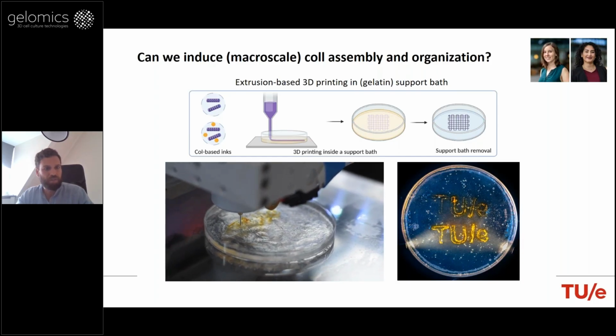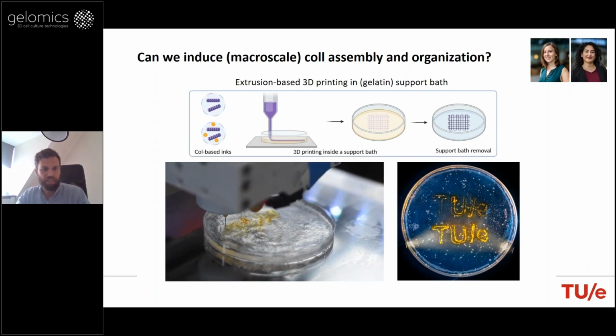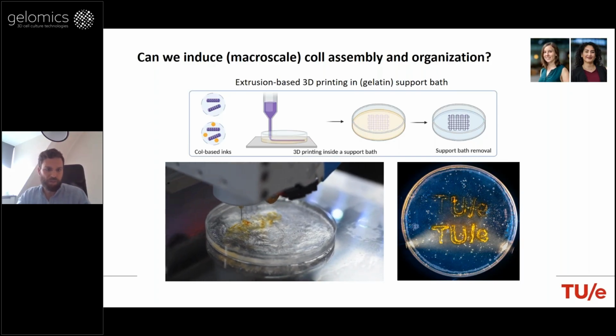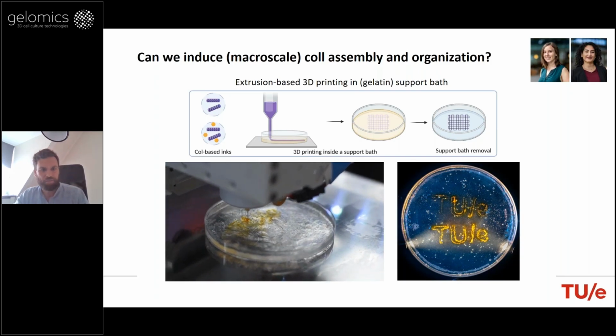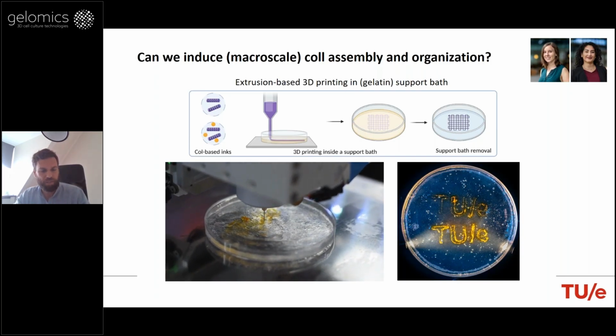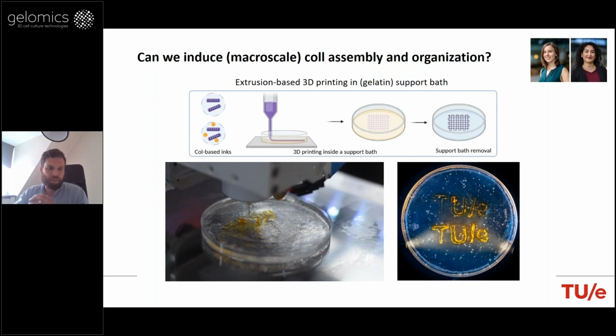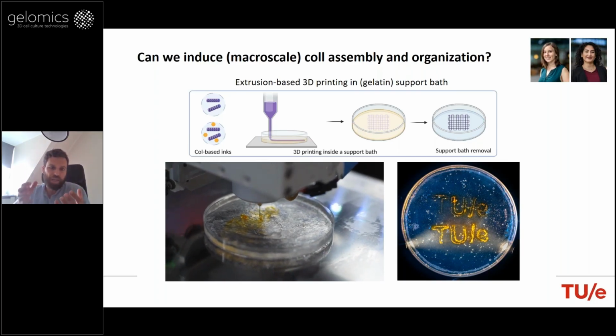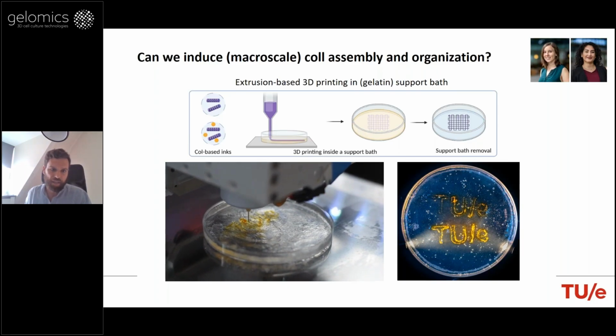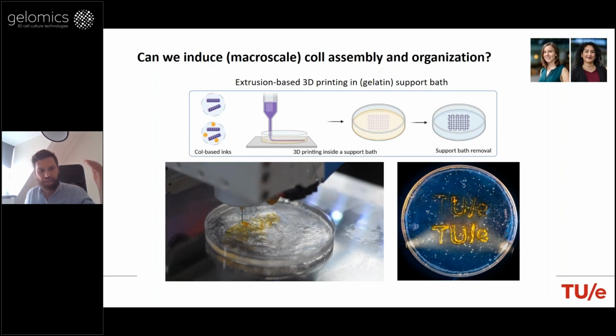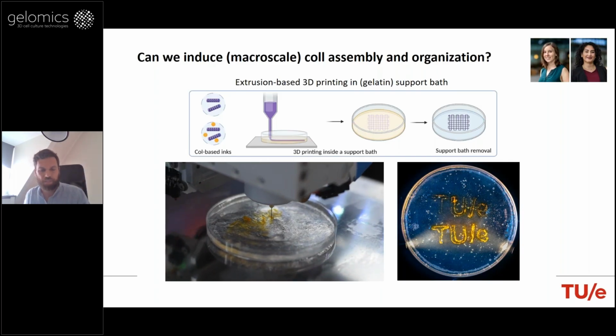So how the process goes, you can see here in this movie, and it's already an established process in the field. The main novelty now is the inclusion of the crowding agents in our ink. You see basically the nozzle traveling inside of the support bath composed of the gelatin granules that basically provides support to the liquid-like ink that we are extruding. And then by repeating layer by layer, we could achieve our 3D scaffolds.